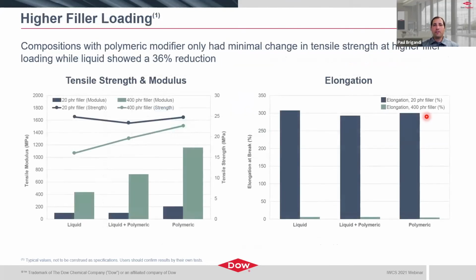So here we wanted to look at the effect of filler loading. So many of the high performance, particularly the low smoke, applications require the PVC to be formulated even further. So incorporation of smoke suppressants and other additives to be able to meet those stringent requirements. And what we're showing here, again, want to emphasize just really a simplified example to show what you can do when you take these materials and formulate in your compositions. The polymer modifier here, if we look at the tensile strength and the modulus, we're going to compare liquid to polymeric, but we've also blended or mixed the two. So it is possible to use the polymeric as a partial replacement or in combination with liquid as well.